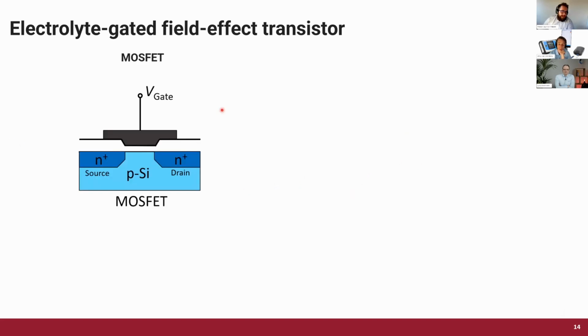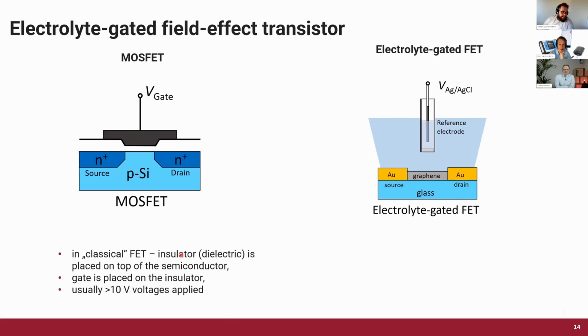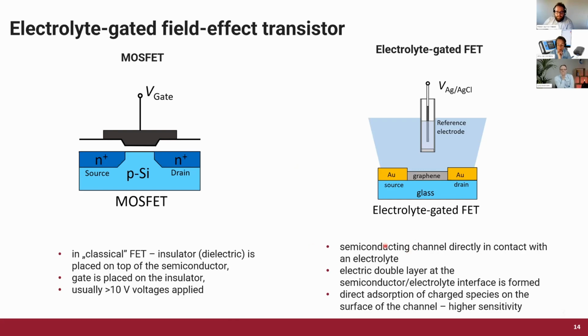So comparing the electrolyte-gated FETs with the classical MOSFET, as we see in here, there is a dielectric insulator on top of the semiconducting channel and below the gate, so to say. The gate is placed on the insulator, and usually voltages above 10 volts are applied, although it varies from MOSFET to MOSFET, obviously. And in the electrolyte-gated configuration, we have the semiconducting channel directly in contact with the electrolyte, and then what serves as our dielectric is the electric double layer at the semiconductor-electrolyte interface, and then the direct adsorption of charged species on the surface of the channel gives a direct addition to the current-voltage characteristics of the FET, which yields higher sensitivity in principle.